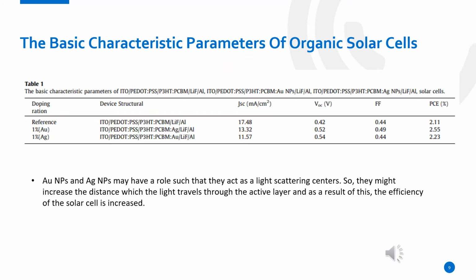This table shows the basic characteristic parameters of organic solar cells. According to our results, the open circuit voltage in the fourth column and power conversion efficiency (PCE) of the organic cells have increased after Au nanoparticles and Ag nanoparticles doping. It increased from 2.11% to 2.55% after doping Au nanoparticles and from 2.11 to 2.23% after doping Ag nanoparticles in our organic solar cell configuration. Au nanoparticles and Ag nanoparticles may act as light scattering centers, so they might increase the distance which the light travels through the active layer, and as a result of this, the efficiency of solar cells increases.